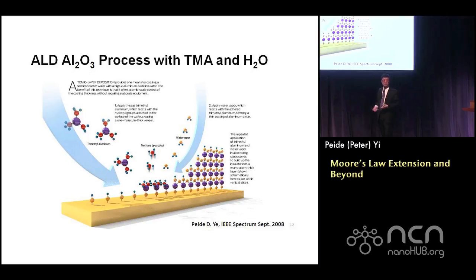So we first purge and get chemical A adsorbed on the surface of the substrate. Because it's adsorbed, it can only cover the surface. It cannot put a second molecule on top of the first molecule already adsorbed on the surface. That's why it's a self-limited process. At time 1, you put chemical A on the surface. At time 2, you put in chemical B, which reacts with chemical A. So eventually, you can grow, atomic layer by atomic layer, a compound C, such as aluminum oxide.